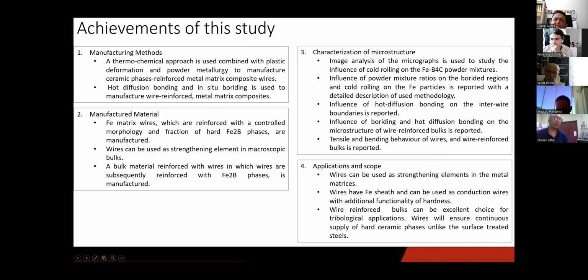And the reason that a softer material is combined with the contradicting high hardness of the material is that while the wear tests are occurring, the debris during the wear applications can be embedded in the softer sheath, in the softer steel, and we can prevent the three-body abrasion in such applications. And there is going to be a continuous supply of iron boride phases, no matter how long you use the material, unless it finishes, unlike the surface borided materials, in which eventually the hard layer of the material is removed, and the hard layer of the borided steels is not connected cohesively with the host material. In the material which I have used, such a thing is not an option, because all wires are cohesively bonded.